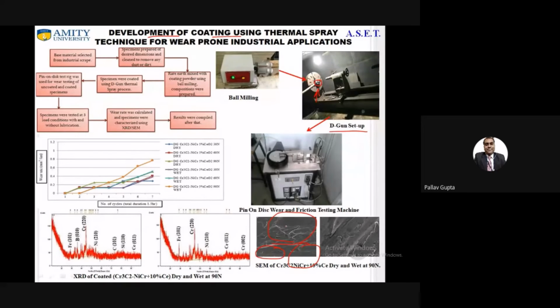Now, on an overall basis, we have also done one study, a life assessment, in which we found that when we are using boron steel in normal condition, and when we have coated it with Cr3C2 NiCr with 5% and 10% cerium oxide, the life was found to be improved by around 15 years. Life assessment was something I was discussing in the first few slides, that is the performance of the material. So the performance was improved by 15 years, 1-5. This is essentially very much important.